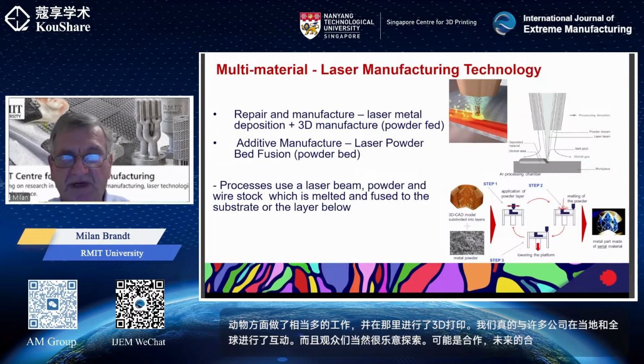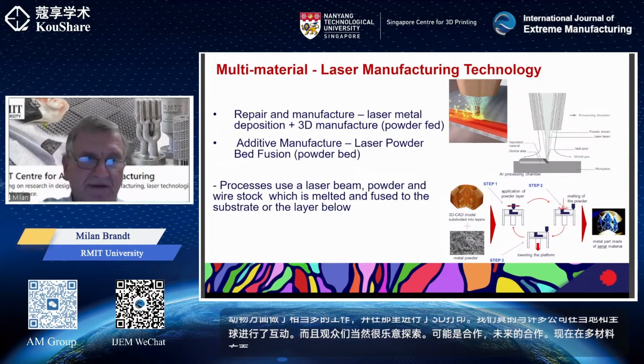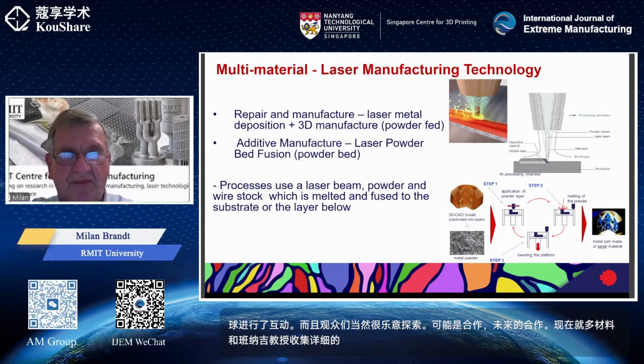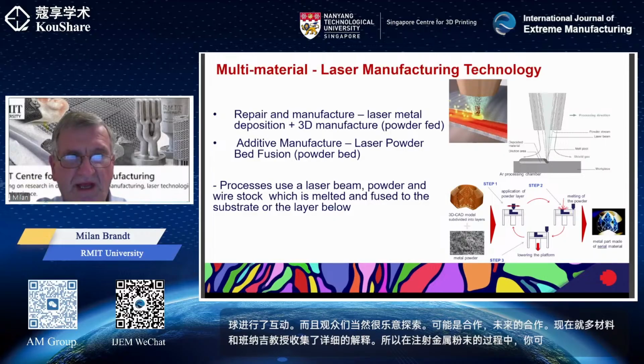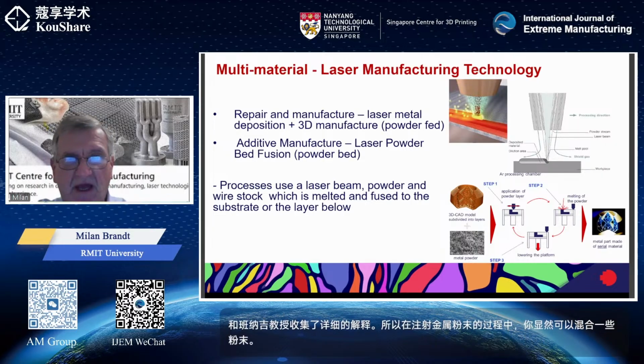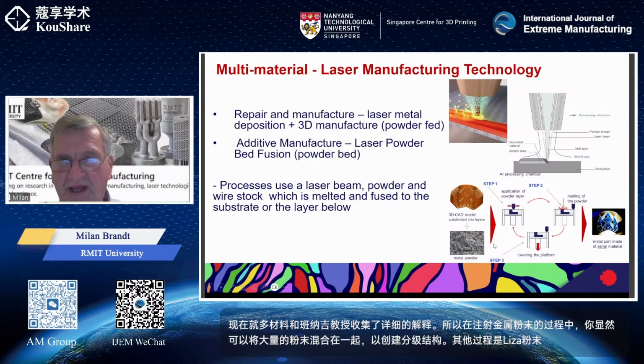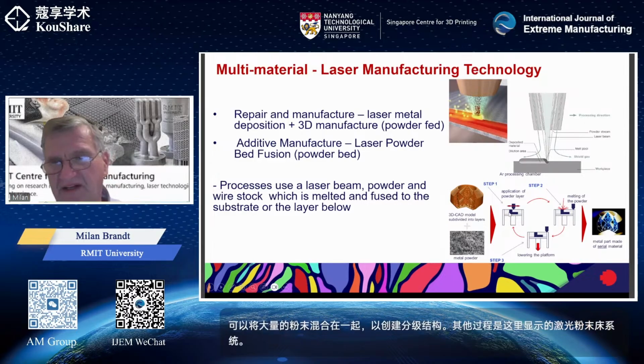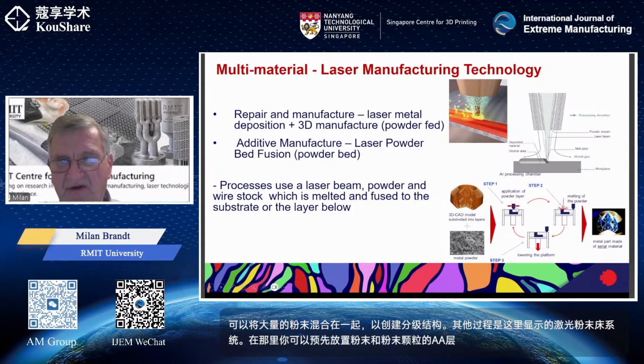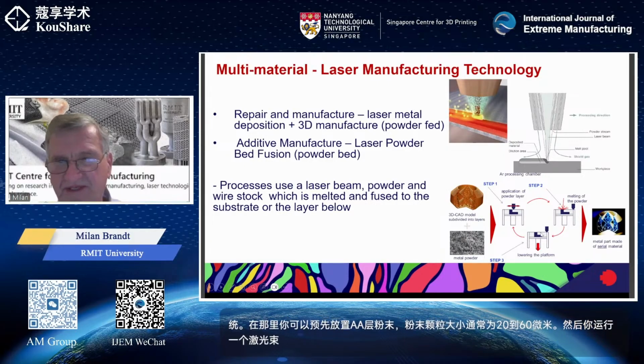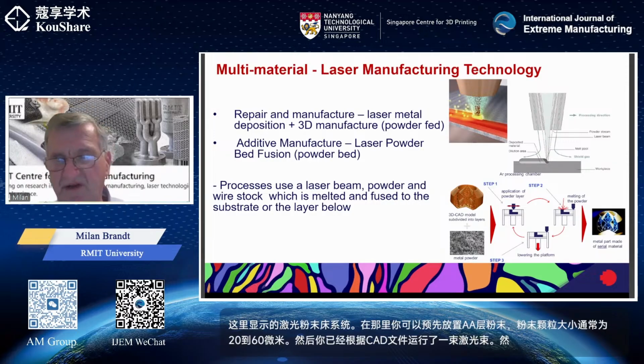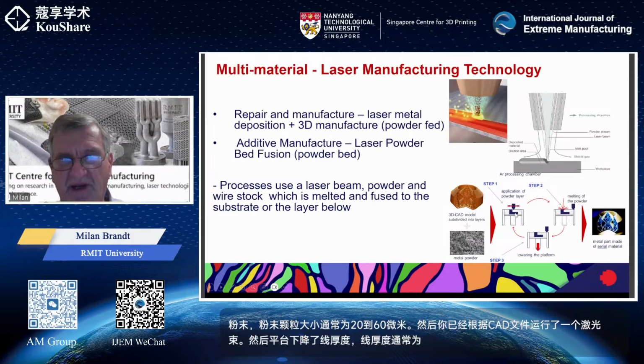Now, in terms of multi-material, Professor Banerjee gave a detailed explanation of the DED process where you're injecting metal powder, and you can obviously mix a number of powders together to create graded structures. The other process is the laser powder bed system shown here, where you pre-place a layer of powder, and powder particle size is typically 20 to 60 microns. And then you run a laser beam over it based on the CAD file. And then the platform descends by the layer thickness, and the layer thickness is typically 30 microns. And then another layer of powder is pre-placed, and then the process is repeated.